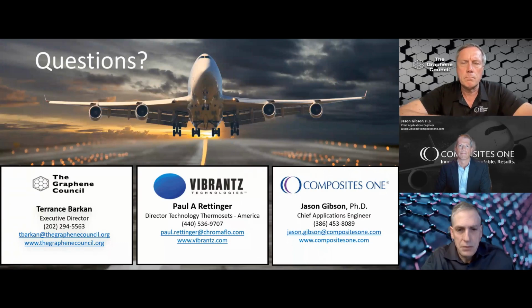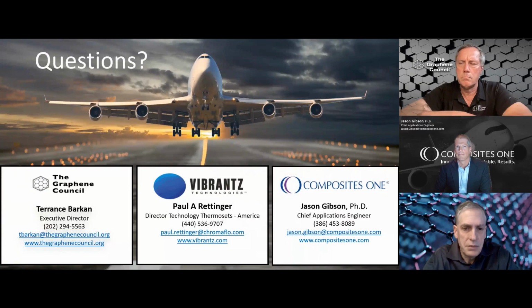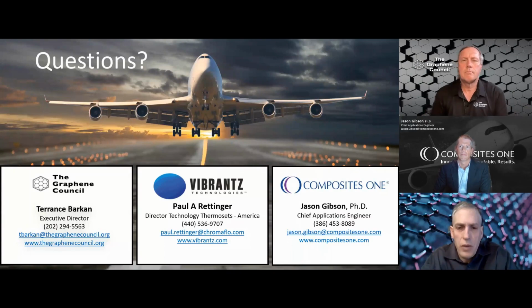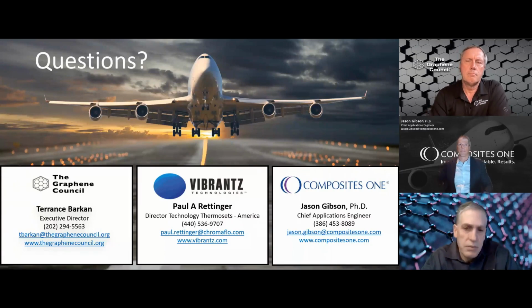All right, excellent. Within the study, how did you evaluate the resin wettability on the graphene or graphite interlayer spaces in the carbon materials? How do we evaluate the interwettability? Resin wettability? Rheometrically. We looked at, when we started off with the raw powder, we took a measurement at various shear rates on the material as dispersed at various loadings, and then we changed the loadings, and then we dispersed it to varying degrees, and we measured the change. Okay.